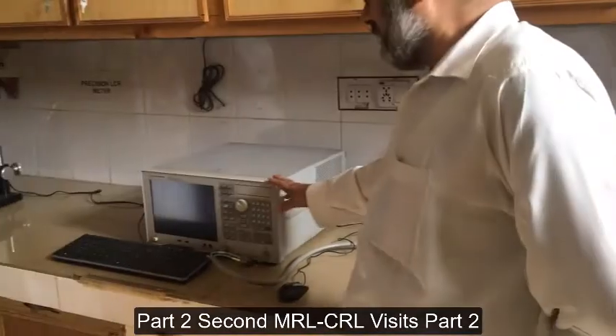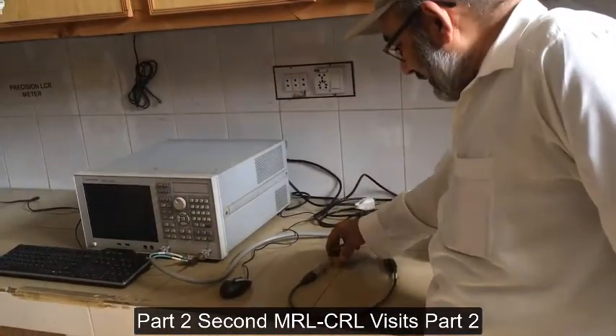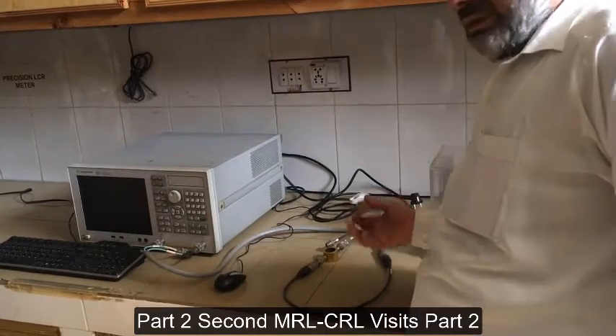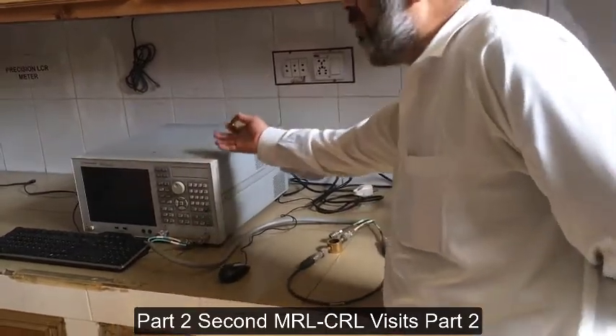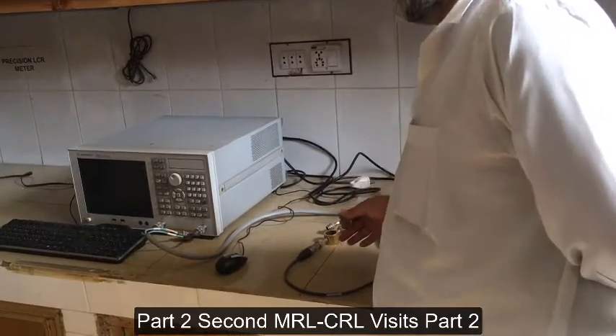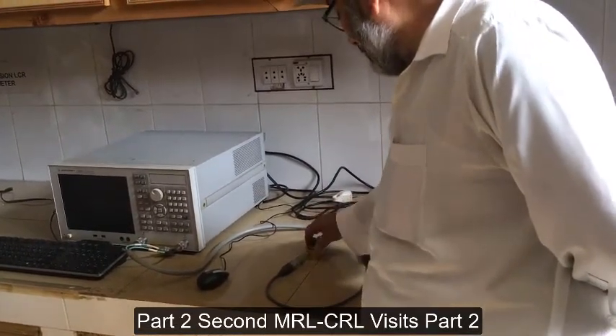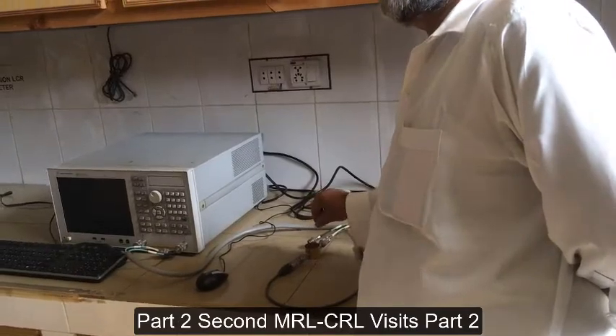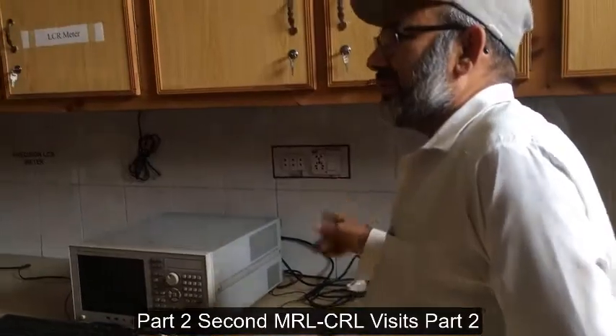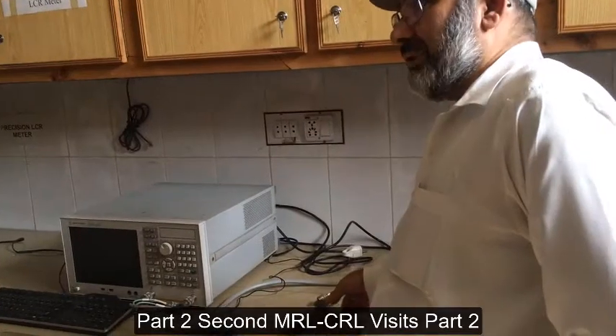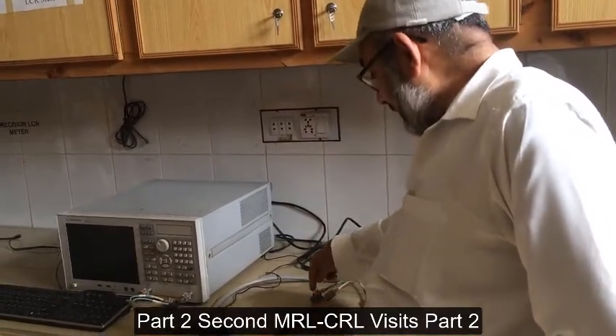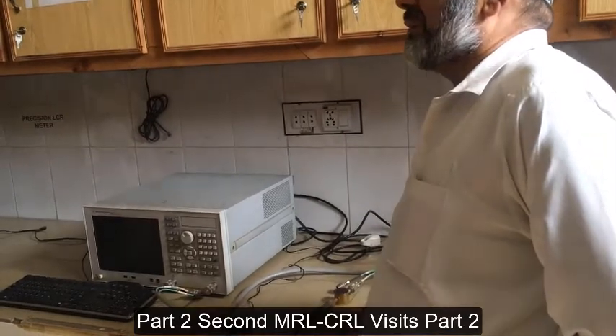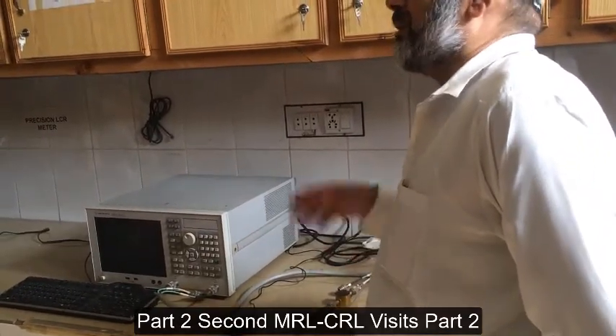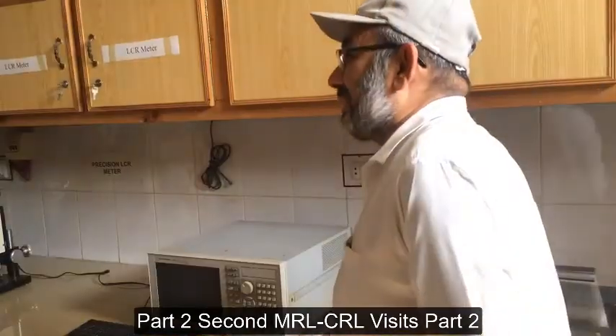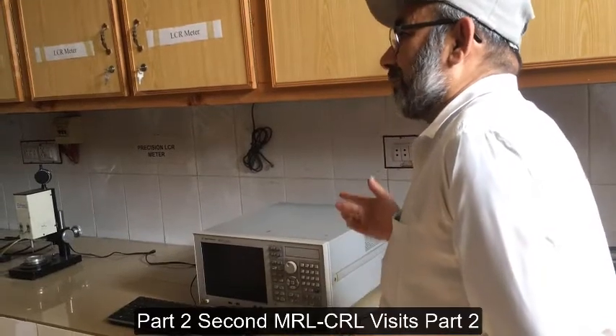This is a network analyzer, and these small cavities are prepared here. We buy the box, but then we make the circuits ourselves, and this gives you the true environment of a cavity resonator, and you measure the temperature coefficient of resonant frequency because you change the temperature. You put it on a hot plate, put a thermocouple in this hole, and you measure the temperature coefficient of resonant frequency. This means that if you are using a device in Peshawar, is it usable in a snowy area, for example?